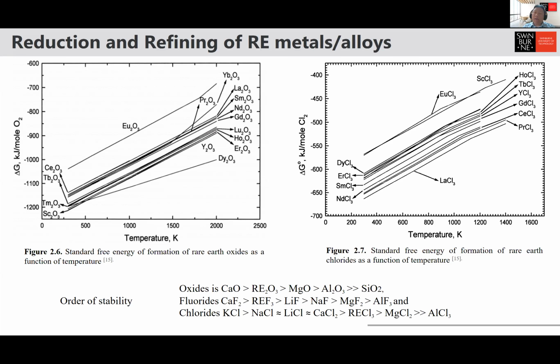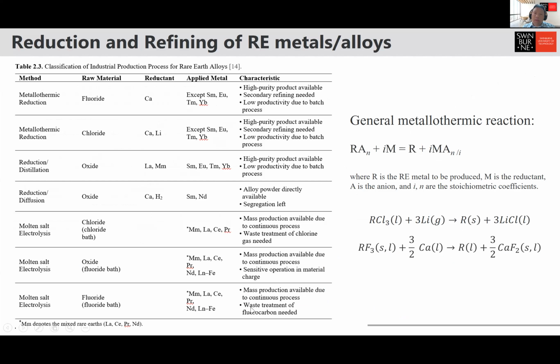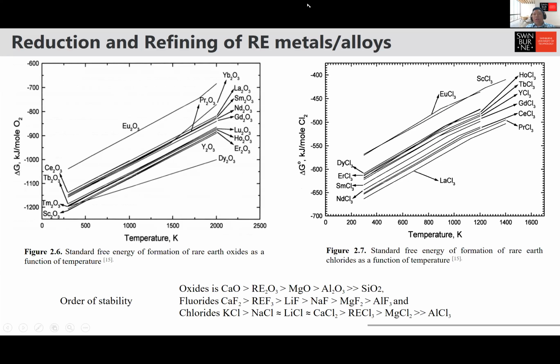So another thing for you to understand here, considering this graph, is that when you have a slag, such as steel making slag, for example, or slag from blast furnace, or even copper making slag, right? Which is very calcium silicate slag, right? And then you process these rare elements in the circuits of iron making, steel making, and copper making. They will end up in the slag, right?